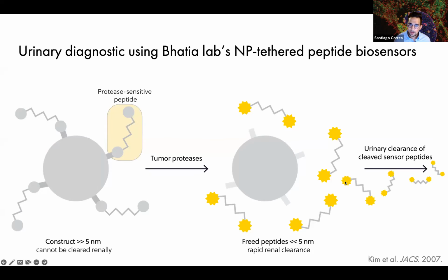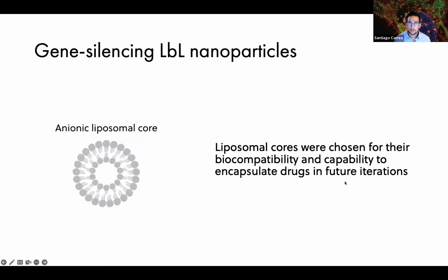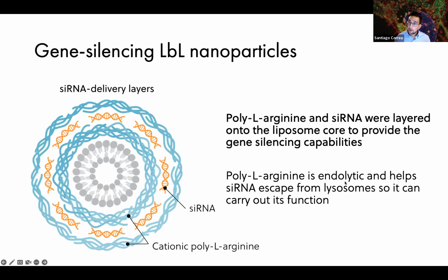And so the goal was to combine that protease technology with our gene silencing layer-by-layer nanoparticle system. And so I'll give the overall view on this system using that same kind of anatomy as before. Our core substrate here was an anionic liposomal core material, which we had chosen due to the translational relevance of lipid nanotechnology. And then our inner polymer layers consisted of polyarginine and small interfering RNA, or siRNA. And so these inner layers essentially introduce the gene delivery components in this nanomaterial. The polyarginine allows the nanoparticle to escape into the cytoplasm, and the siRNA ultimately is what prevents expression of a